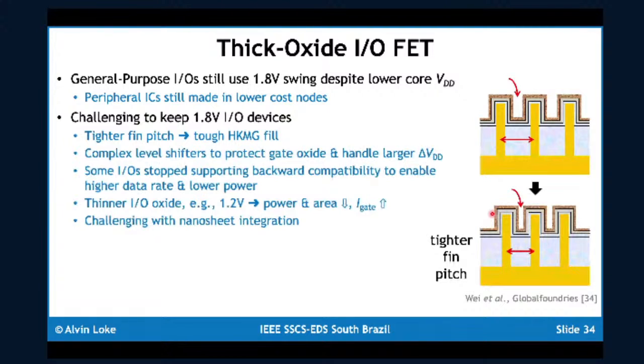It is a challenge to keep these I/O devices for a host of different reasons. The main one from a technology perspective is, as you scale the fin pitch down lower and lower, your replacement metal gate process has a much more challenging time to deposit a thicker dielectric—shown here as the blue, light blue, and gray regions, which is the dielectric you need to deposit for a thicker oxide IO FET. It is also tougher to build level shifters in this process, because you need to bridge a larger supply voltage difference.